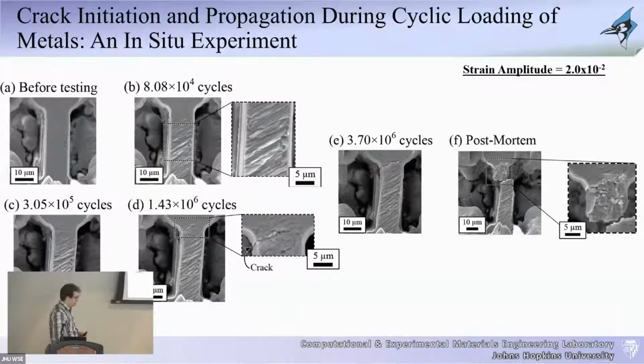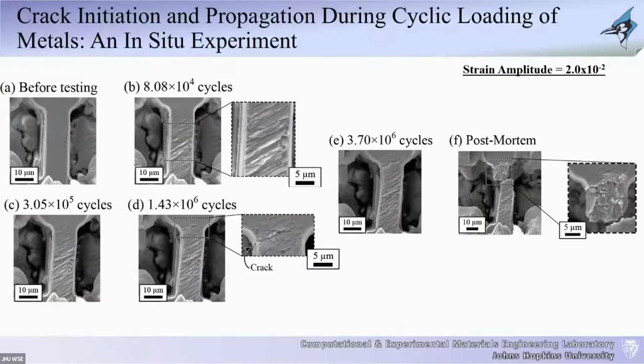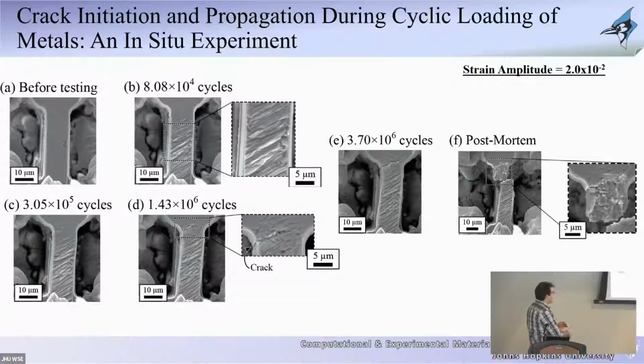Skip the image on the right due to the time. But if you take this a step further, there was no fracture in that experiment. We stopped that experiment. We were particularly focused on the persistent slip bands. We took this a step further and we continue cyclically loading these samples. So this is another experiment, but at a higher strain amplitude. And you can actually observe in this case, as the number of cycles increases, eventually a crack nucleates, the crack propagates, eventually creating complete fracture in the sample.